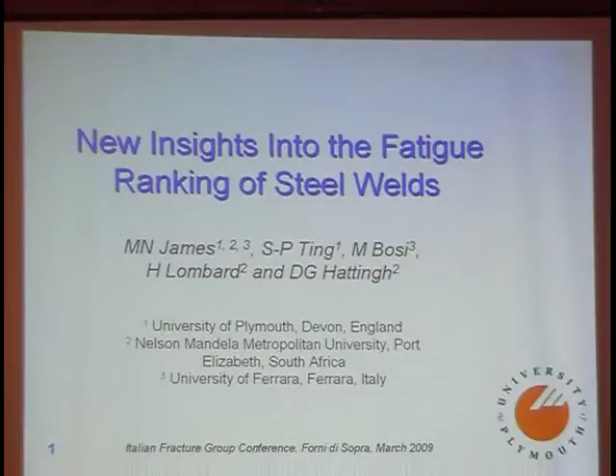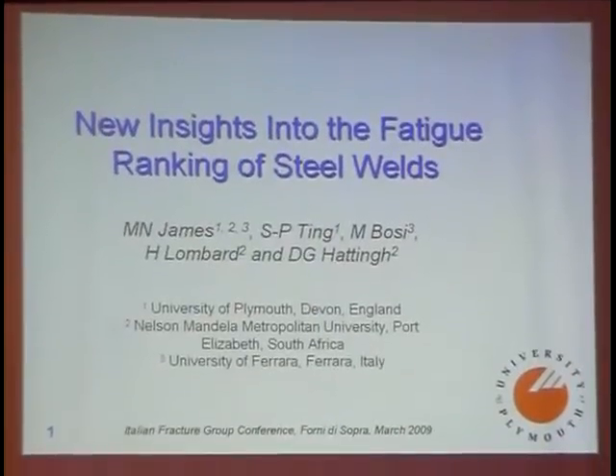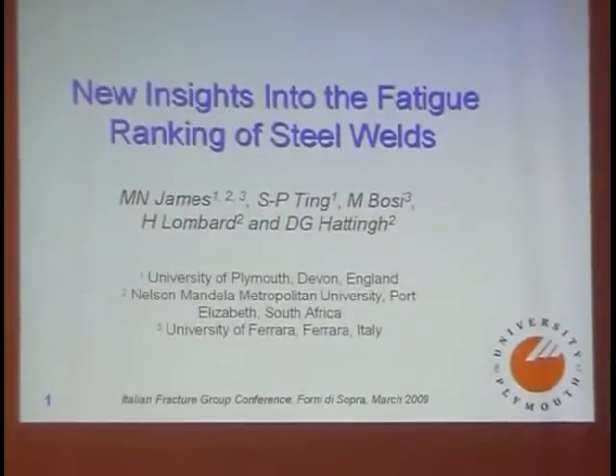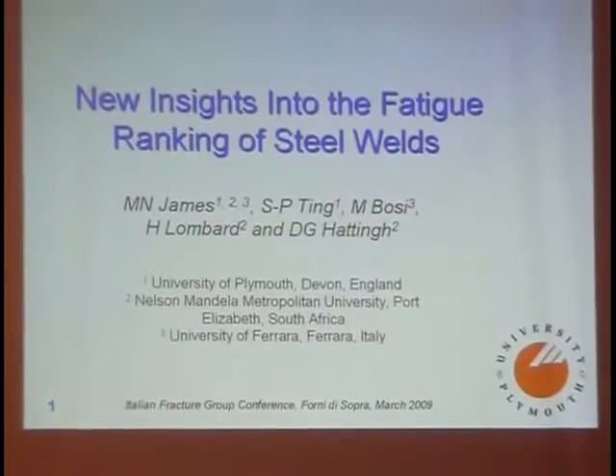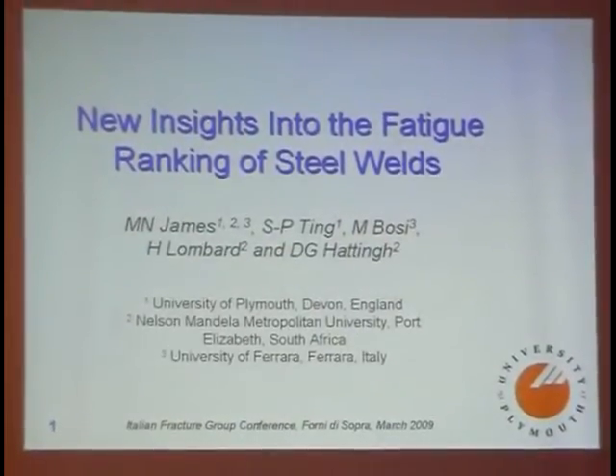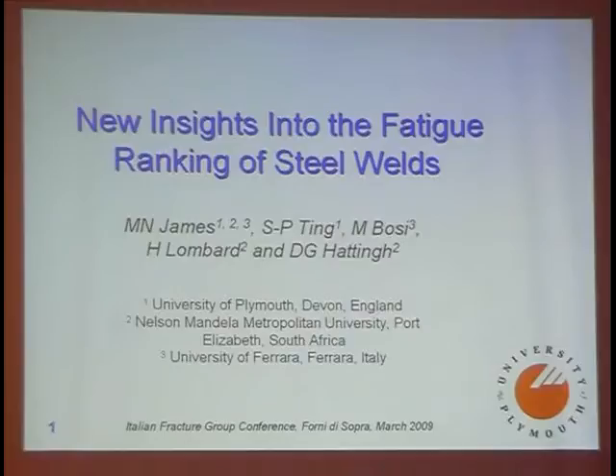And particularly in the case of welds, you have microstructural influences and heat input influences, and they lead to microhardness gradients and to residual stress gradients. So in this I've had a go at characterizing the residual stress and microhardness gradients for a variety of welds, to see whether one might be able to predict the fatigue ranking of a variety of welds from some aspects of the microhardness and the residual strain. It turns out that you probably can, but probably my data set is not big enough.